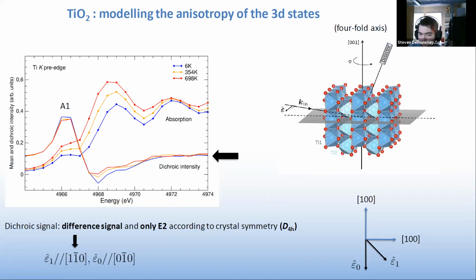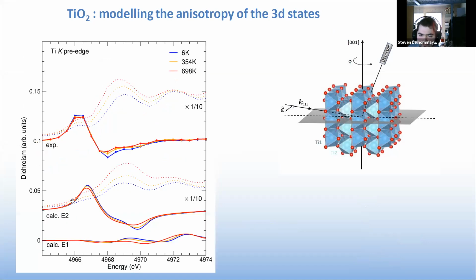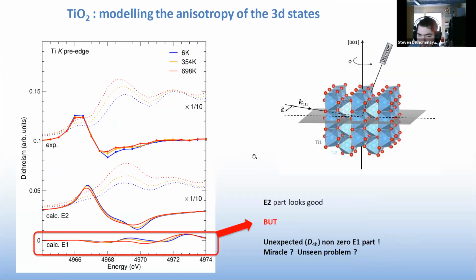But when we try with our method to simulate this signal, here is what we get. Here is the E2 contribution, here is the E1 contribution. And as you can see, there is a big problem that I can help you figure out by surrounding it in big flashy red color. Here the problem is that even if the E2 signal resembles the experimental signal quite well, I don't have much time, I will go fast, we have a non-zero E1 part that is completely unexpected. And so either we have a miracle on our end or an unseen problem.